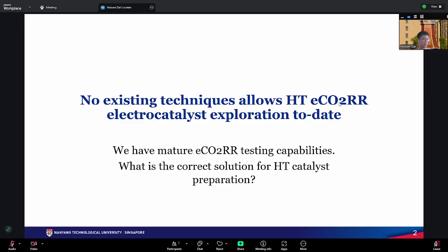The first reason is that there are no existing techniques that allow high throughput ECO2RR electrocatalytic exploration to date. If you want to make ternary samples and make a DOE table, it's going to get crazy, and there's no method to do that. Second, even if somebody tried to do it low throughput, preparing a few samples, it's highly likely not going to be as good as the binary samples, which are highly optimized. So eventually it comes to the throughput of making and the throughput of testing.